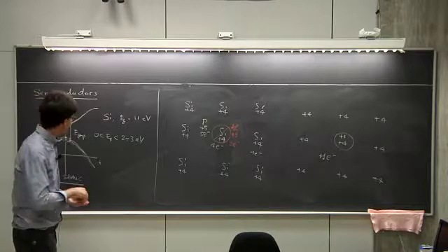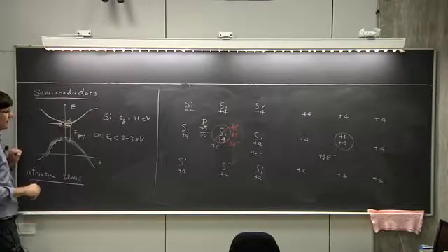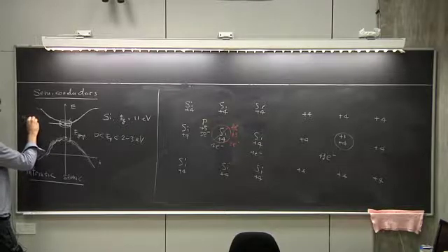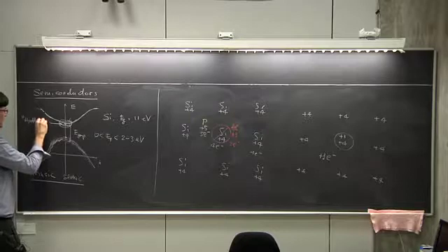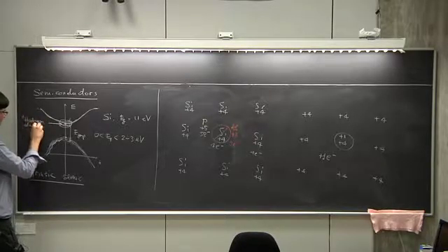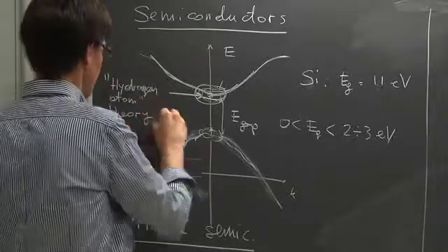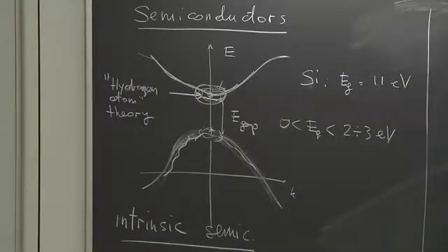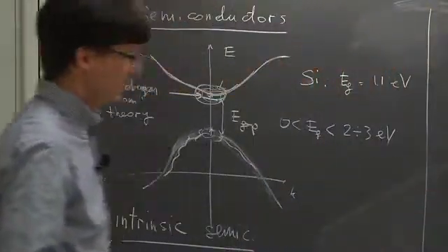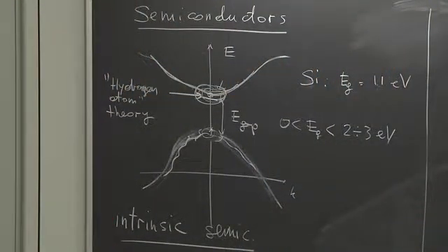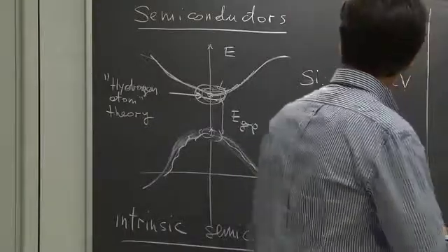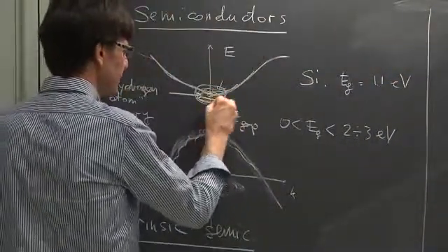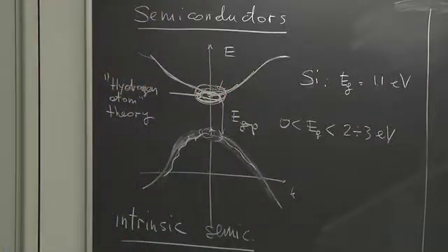Okay? So this is just to say that the position of these states here can be understood based on a quasi-hydrogen atom theory. I don't want to go into the details of that because it's too complicated, but I hope you get a perception of this, right? Because at the end, this is just a hydrogen problem embedded into a pre-existing charge density due to the silicon structure. So the result of all the discussion is that if I introduce a phosphorus atom, I'm going to place an electron somewhere here at the bottom of the conduction band. That's the message I would like you to keep in mind at this point.